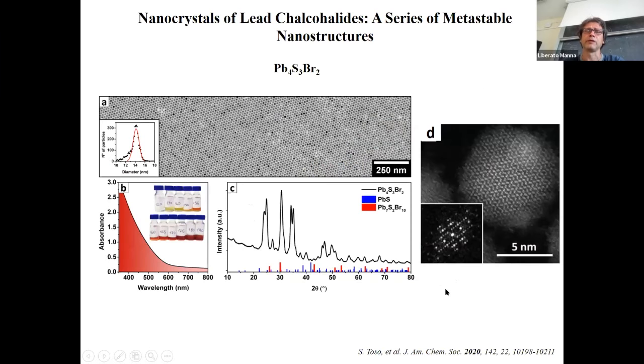Okay. Now, still looking for ways to prevent transformations in nanocrystals, we take a slight detour and look into lead-4 sulfur-3 bromide-2. This is a chalcohalide. These nanocrystals were recently discovered by us. They have a phase which does not correspond to any known bulk phase. They have an indirect band gap and basically no emission.